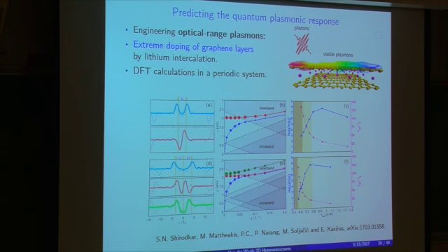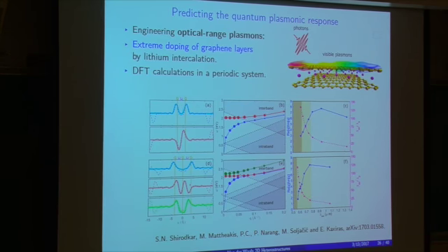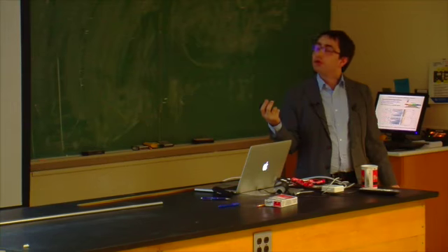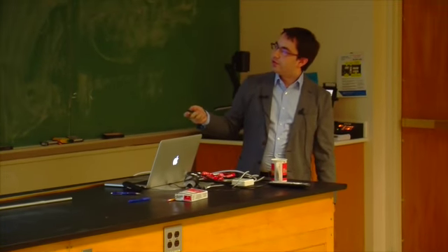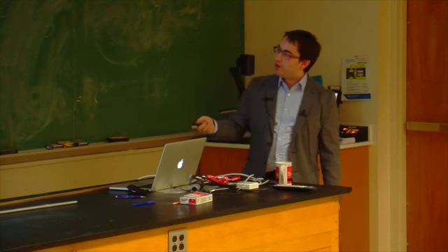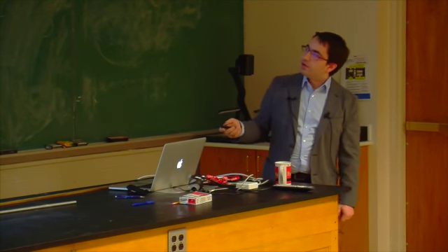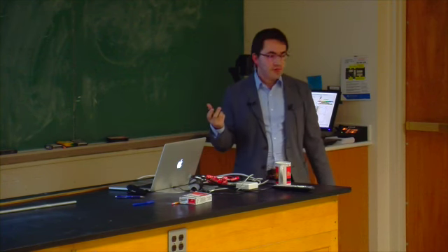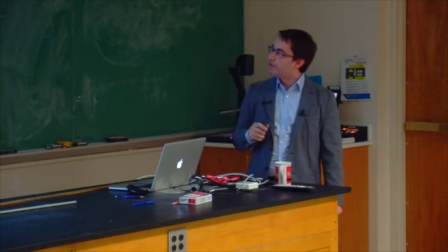And this, we predict, will happen if we actually put, for example, a system of 2 layers of graphene, like here, and we dope this system very highly by putting some lithium in between the 2 layers of graphene. So by putting lithium, which gives a lot of electrons to the system very readily, we push the Fermi level very high, and this doping will produce very different response to the electromagnetic fields. And in particular, using DFT calculations, what we have predicted is that there will be plasmons appearing with a reasonable lifetime in the optical range.